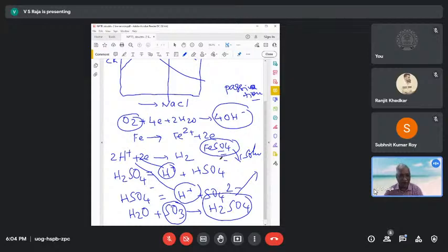So anyway, the point I'm trying to say is that the dissociation of sulfuric acid is suppressed as you start increasing the sulfuric acid concentration, so the corrosion rate is decreasing. So the mechanism is different. That's why I always say that we need to understand what is happening in this case. I also gave some example about temperatures. Again, temperature changes can also happen. So understanding the phenomena is very important. Okay, I hope that point is clear.